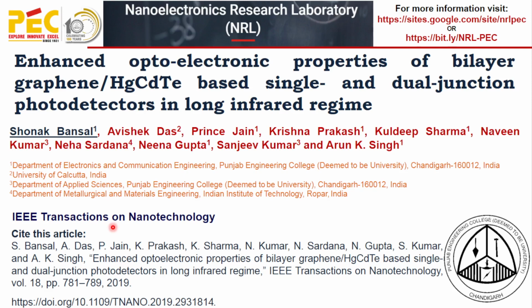The dual heterojunction photodetector is expected to exhibit lower dark-current density and high temperature operation due to lower thermal generation rate than that of the single heterojunction based devices. All the devices demonstrate self-powered mode operation and exhibit better response. And from the results, it was found that external quantum efficiency of more than 100% is achieved in all the devices due to carrier multiplication effect, external biasing, and temperature effect in the bilayer graphene and mercury cadmium telluride heterojunction.